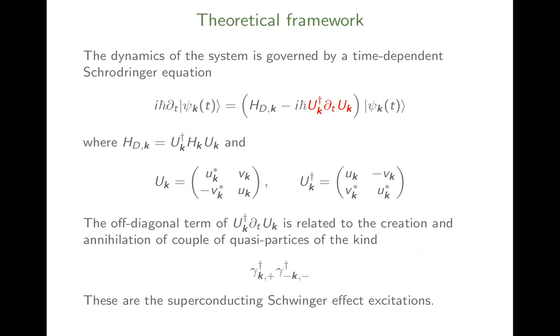You mean the Landau criterion for this? Well, we thought about it. The point is that for this to be true, you need to compute the polarizability of your material, because when you vary the free energy with respect to the electric field, you assume that the polarizability of your material is dependent on the gap and the electric field, and you compute this. The point is that there has been some old computation in the BCS context where they say that the polarizability in the standard superconductor within the BCS model is weakly dependent on the electric field and on the energy gap. So there is no room to apply the Landau criterion here. So you never get an instability of the ground state because the free energy gets higher at a certain point because of the electric field.